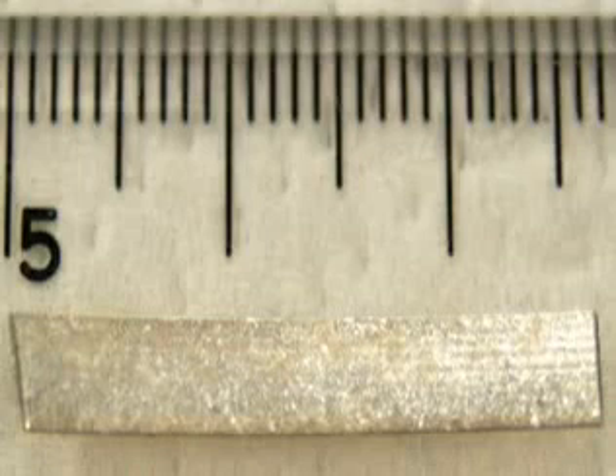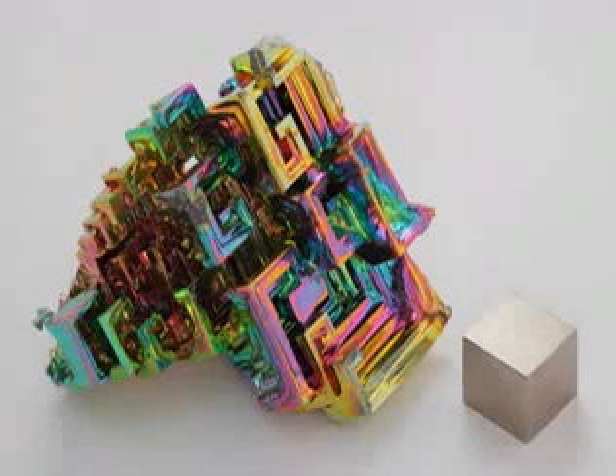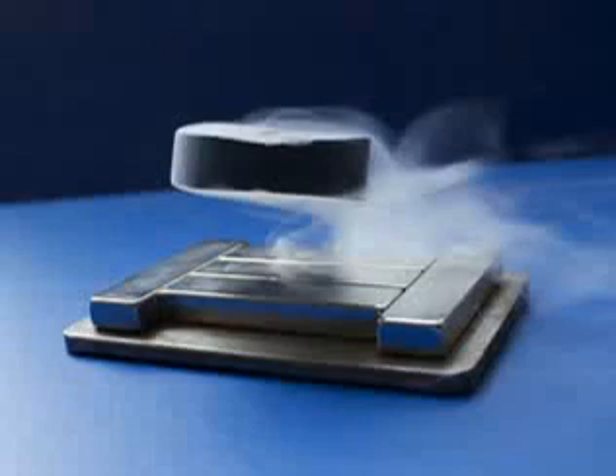The double bismuth oxide layer is only weakly bonded by van der Waals forces. So like graphite or mica, deformation causes slip on these BiO planes, and grains tend to deform into aligned plates. Further, because BSCCO has n equals 1, 2 and 3 members, these naturally tend to accommodate low-angle grain boundaries, so that indeed they remain atomically smooth.